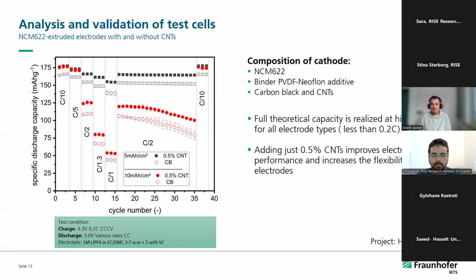And it means that it's still running well, especially at a low C rate. For energy storage, this could be a really good approach. And what we observed is that just adding a small content of carbon nanotubes improves not only the specific discharge capacity, but also the electrode flexibility and mechanical properties.